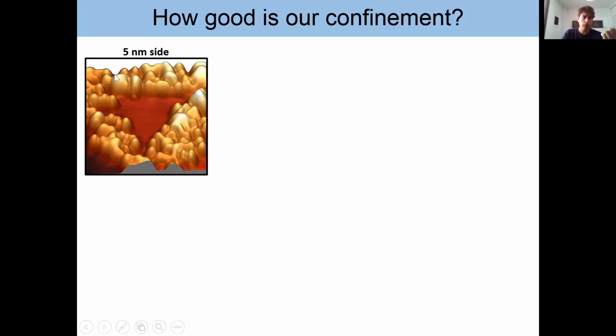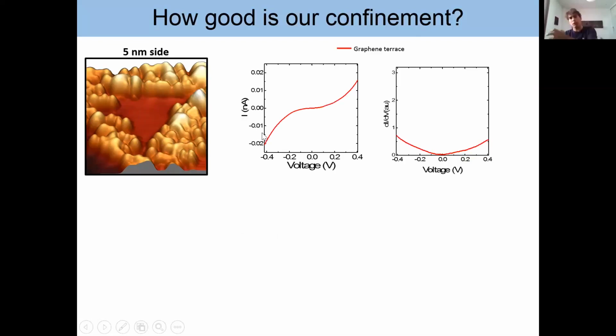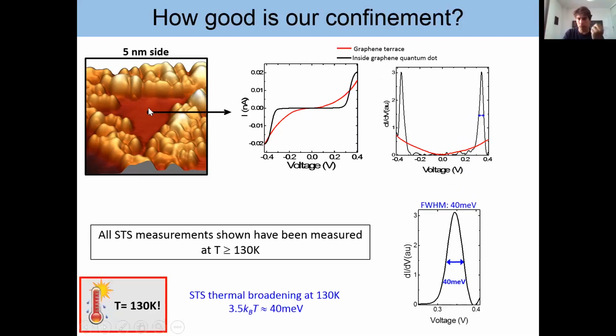Okay, so to do this, here, this is a triangle. First, if I measure a dI/dV curve far away from the triangle, I see this is the standard dI/dV curve for graphene, no gap. And now if I measure the dI/dV inside the graphene triangle, I see immediately the appearance of a very well-defined band gap. And to our resolution, we see how the signal goes to 0 here. And beside this band gap, we can see these 2 peaks, which are the first occupied and empty bound states of our graphene quantum dot.